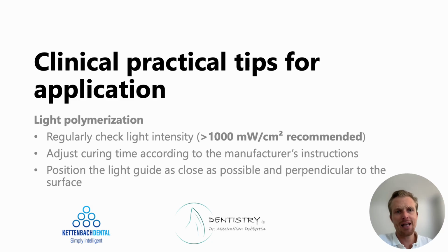So the position of the light is also very important, to be from a right angle straight toward the surface of the restoration, and then of course the period of time used for the polymerization should also be on the sufficient side, so at least 20 seconds when finishing the restoration, so that a final curing, a total depth curing can be enabled.